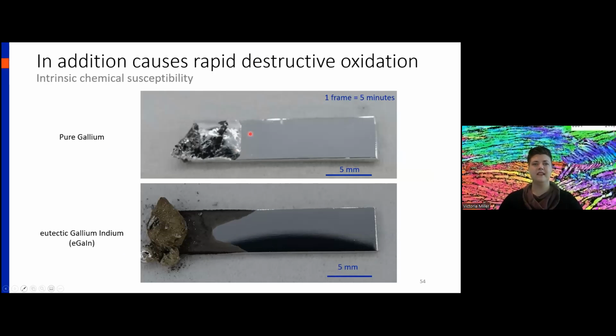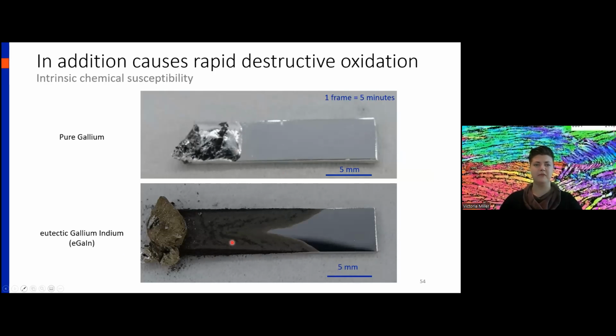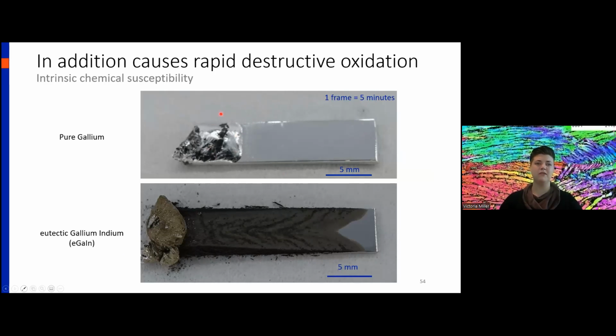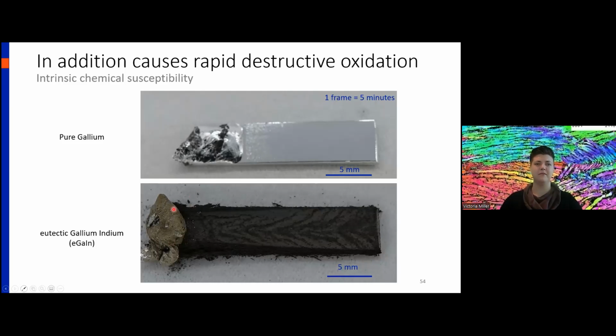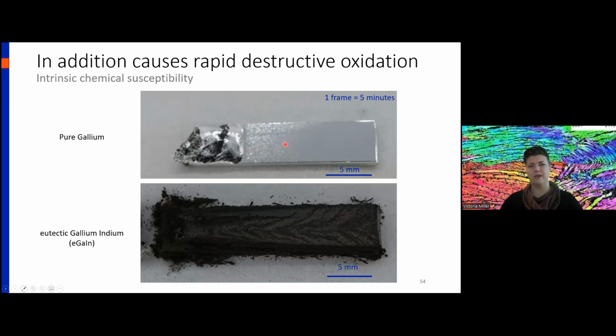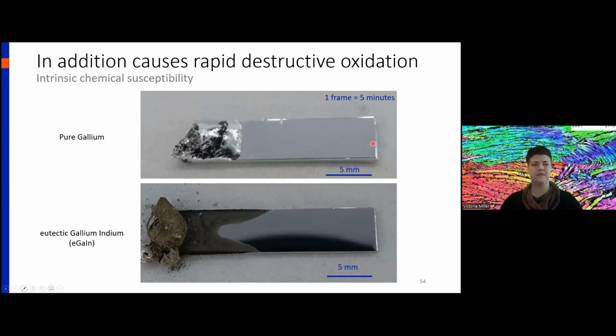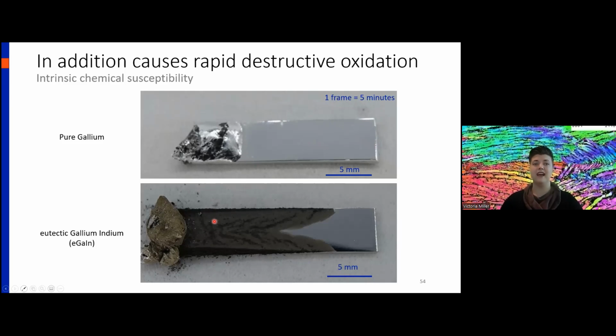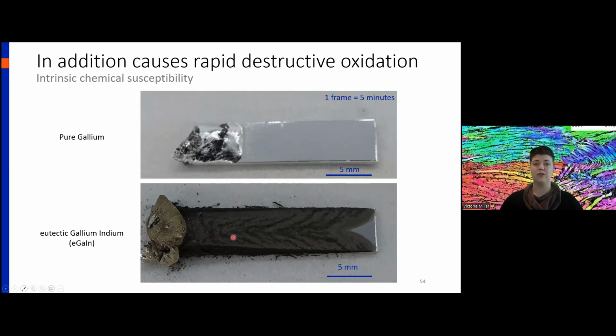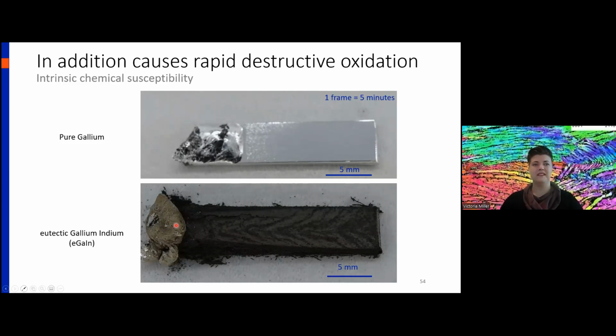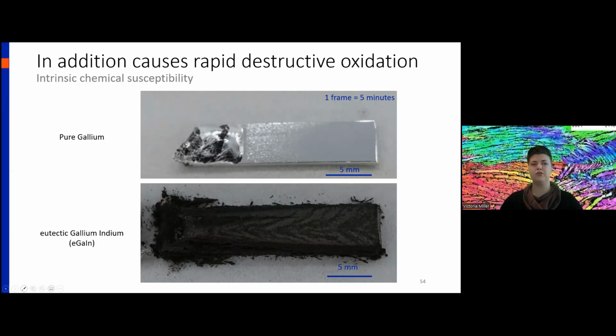So this is an aluminum alloy. This is 5052 aluminum. At the top, it's exposed to pure gallium. At the bottom, it's exposed to eutectic gallium indium. At the top, you can see you're getting just nice grain boundary wetting, and you can see the front propagating across the specimen. At the bottom, you're getting oxidation, and quite a lot of oxidation that propagates across the specimen. And that is just by adding a little bit of indium to your liquid metal.